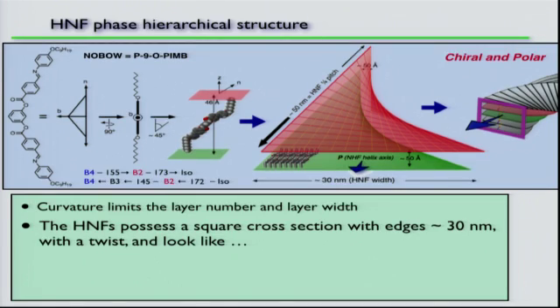So it's the number of layers, and then the width of the layers determined by the strain that comes from trying to make them wider because of the curvature, and this tendency of the top and bottom half layers to stretch in orthogonal directions. And then the layer number ends up giving you about the same height as you have width.